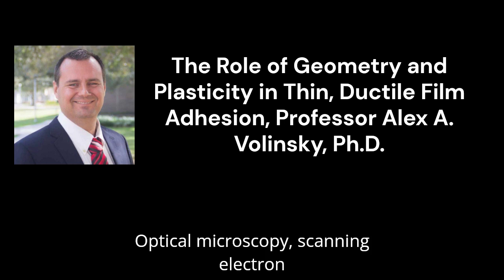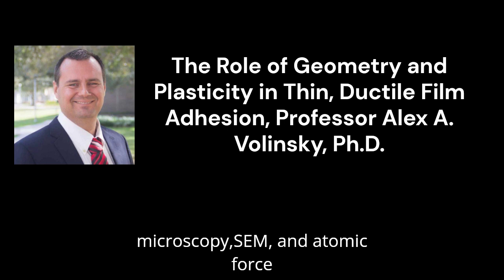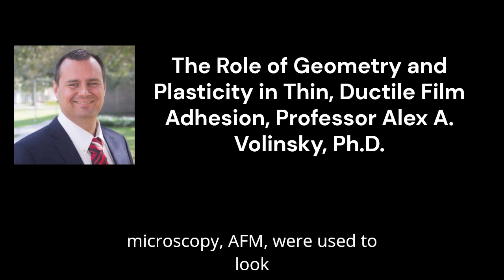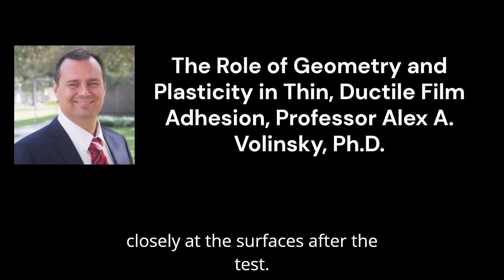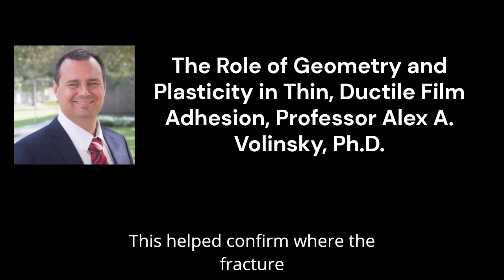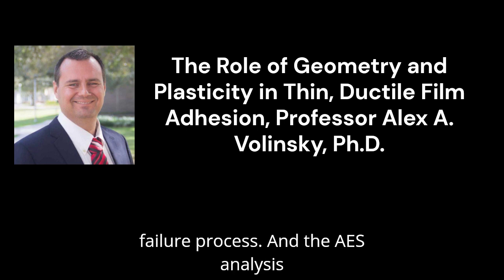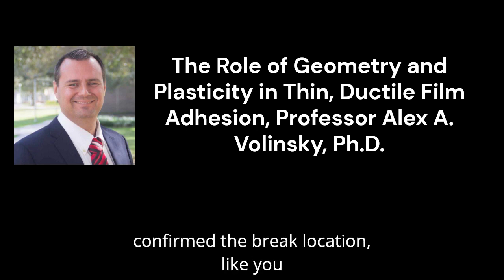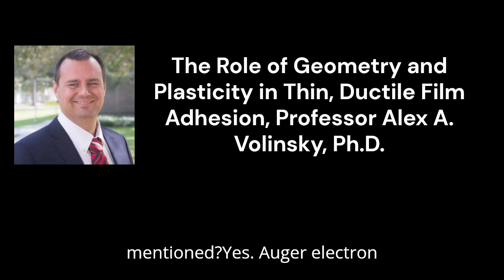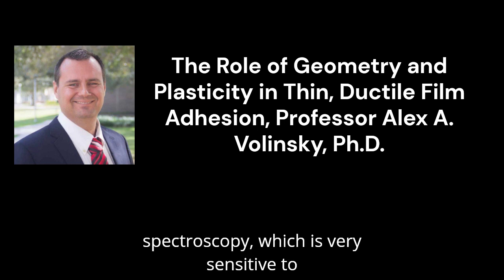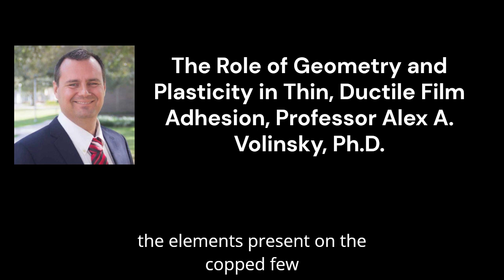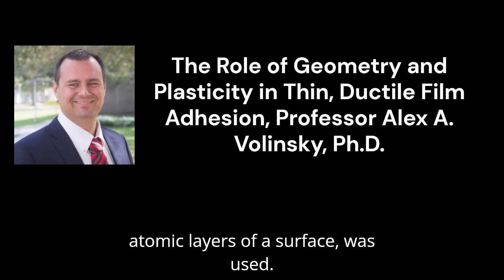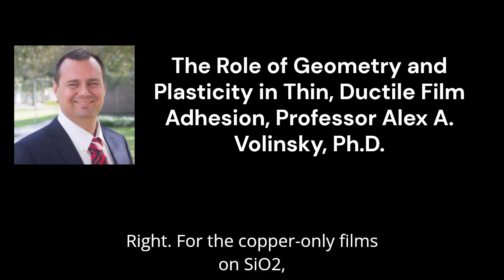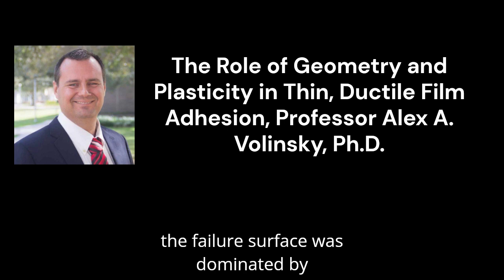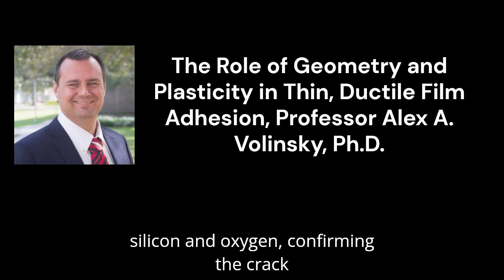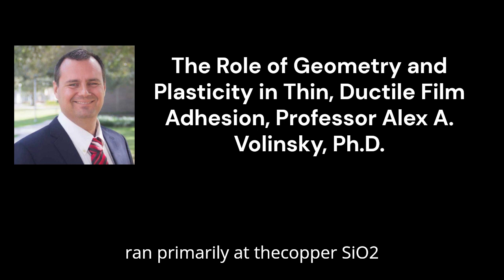Optical microscopy, scanning electron microscopy (SEM), and atomic force microscopy (AFM) were used to look closely at the surfaces after the test. This helped confirm where the fracture occurred and reveal details about the failure process. And the AES analysis confirmed the break location, like you mentioned? Yes. Auger electron spectroscopy, which is very sensitive to the elements present on the few atomic layers of a surface, was used. For the copper-only films on SiO2, the failure surface was dominated by silicon and oxygen, confirming the crack ran primarily at the copper-SiO2 interface.